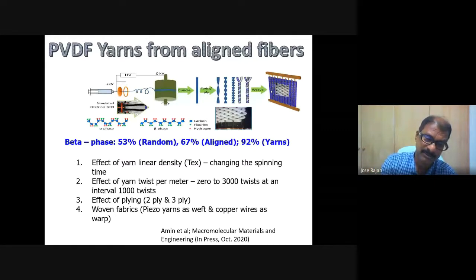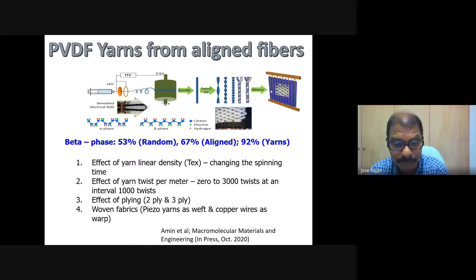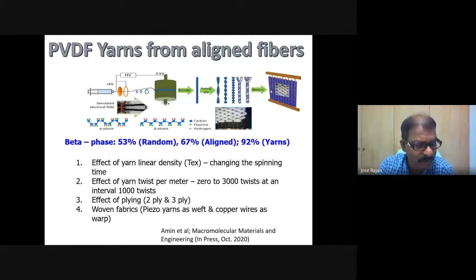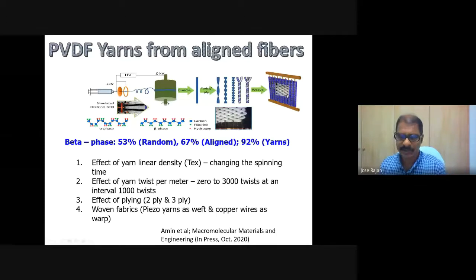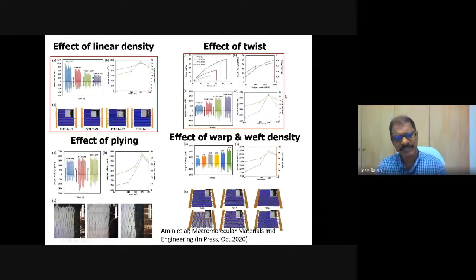We have shown that the best number of fibers in a yarn is about 40. More than that, we get a lower piezoelectric voltage. And twist, we find that about 3,000 twist is good for getting better piezoelectric coefficients. Plying, we find that 3 plying is better than 2 plying and single plying. And the effect of weft and warp density, we find that when there are about 20 weft and warp, then we get the best piezoelectric coefficients. So those are the conventional results we got.